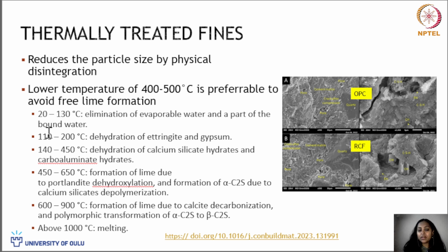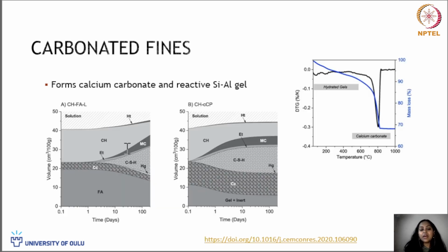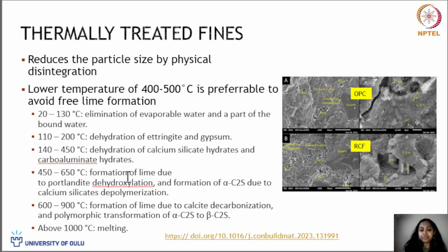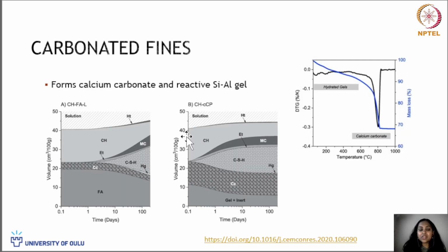It will eliminate the evaporable water and the bound water, and then it will dehydrate ettringite, gypsum, your CSH and aluminate hydrates. And in certain cases, it also forms lime from Portlandite. And then dehydroxylation also happens in this stage around 600 degrees. So these are thermal activation methods by which we can dehydrate and produce a reactive fine fraction, which can be used as a supplementary cement.